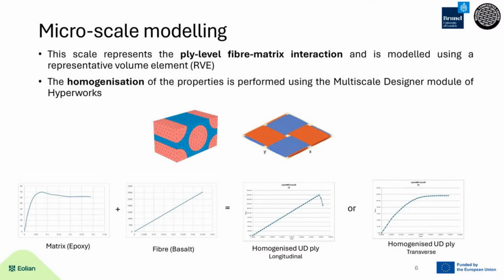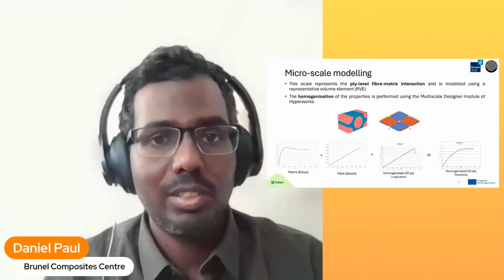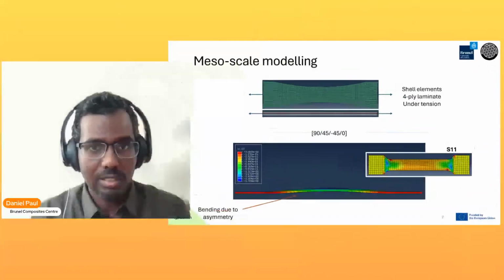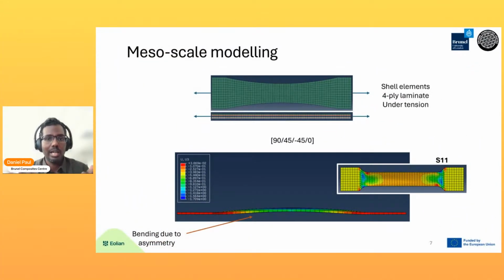And once we have these homogenized ply properties, we can then take them to the mesoscale. By mesoscale, I mean the laminate level. So these are laminate coupon or sample level structures. We take the ply properties, which we have got earlier, and we take them to these multi-layered laminates. And then we can apply different orientations and different geometries, and we can replicate the experimental characterization that we are performing in the simulations.